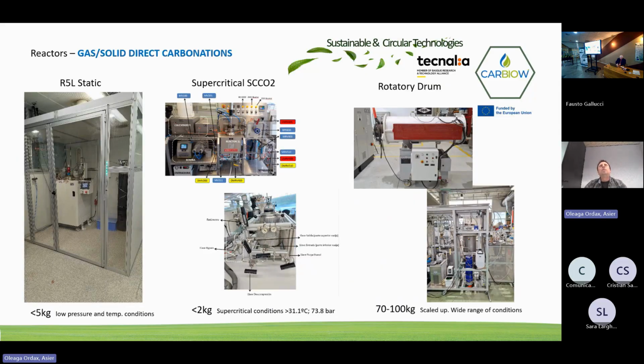So the reactors, we have several reactors. We have other ones, but for this project, we use this static one at the left, less than 5 liters of volume for 5 kilograms of sample. A supercritical reactor that works with supercritical conditions, of course, a bit more complex, and a rotatory drum with multi CO2 fluxes connections for scaling up.